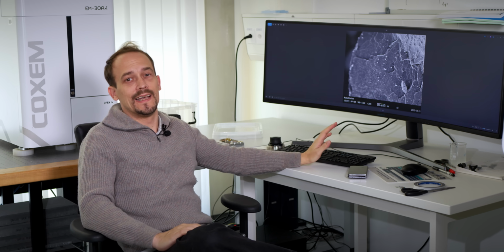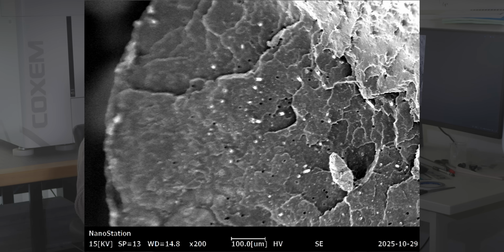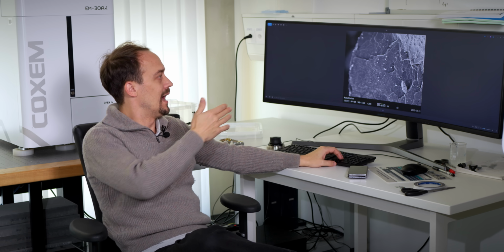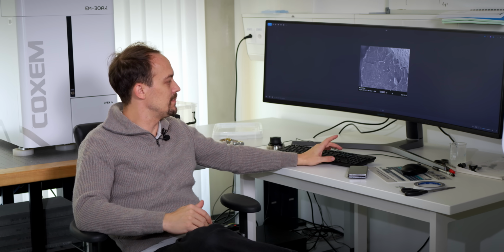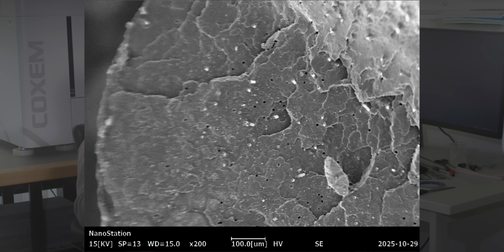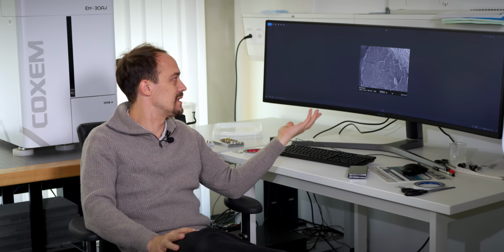Okay, so let's look into our images. So this actually is the undisturbed filament right off the spool. We broke it using liquid nitrogen and we zoomed in. And as you can see on this image, the carbon fiber in the filament itself is in the middle, and outside you have an undisturbed shell of pure PLA. That's something I was expecting because why would they claim it if it's not true that they did it? So this one is not a big surprise.